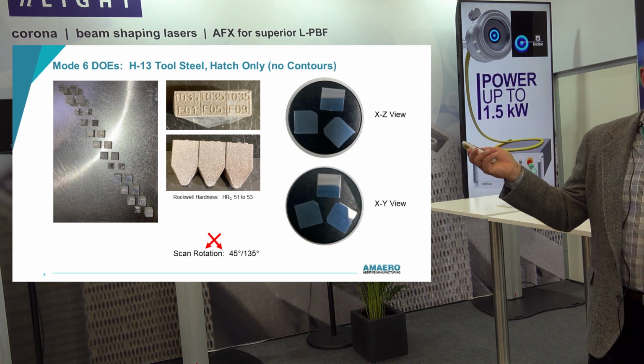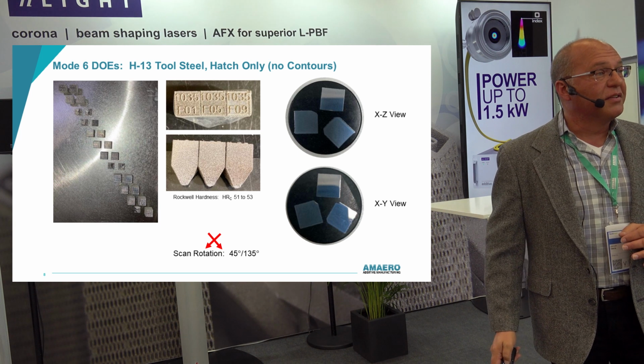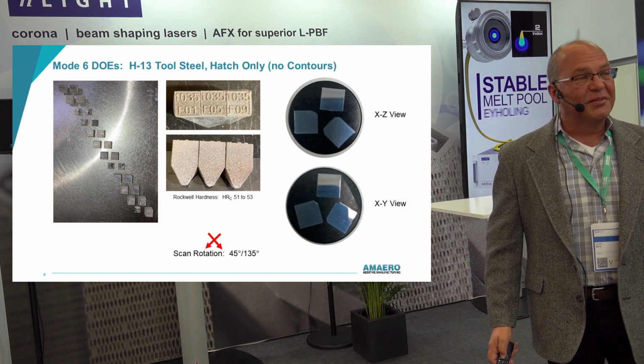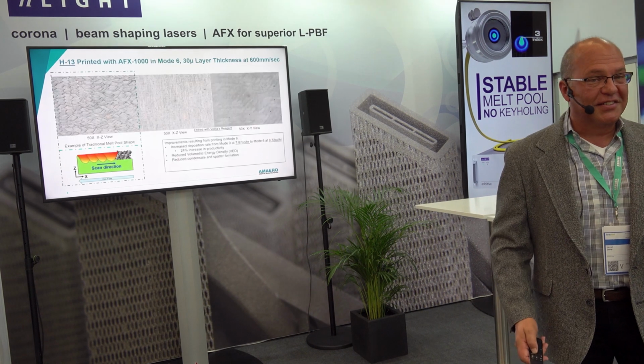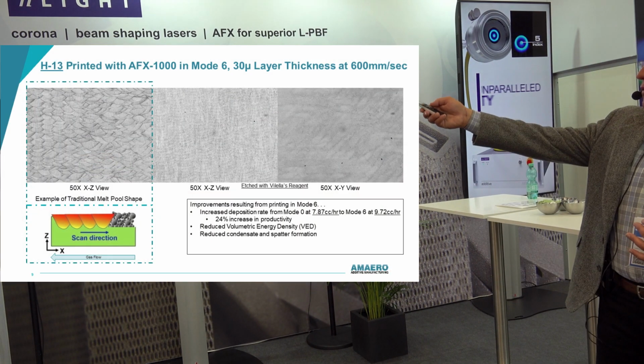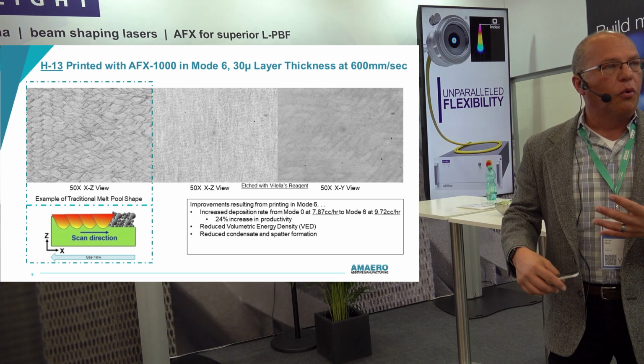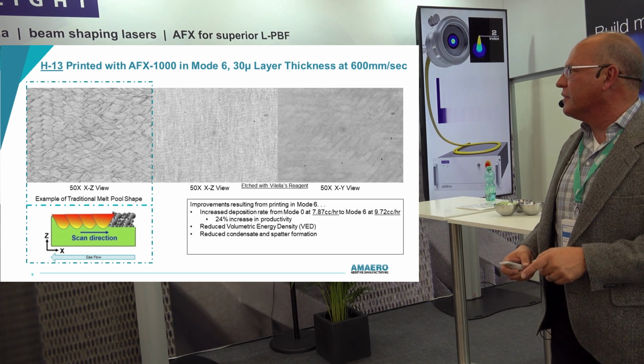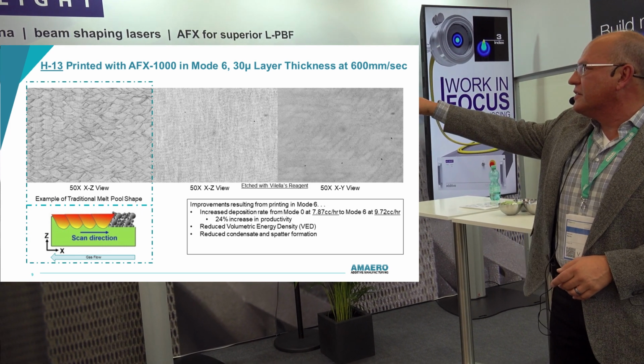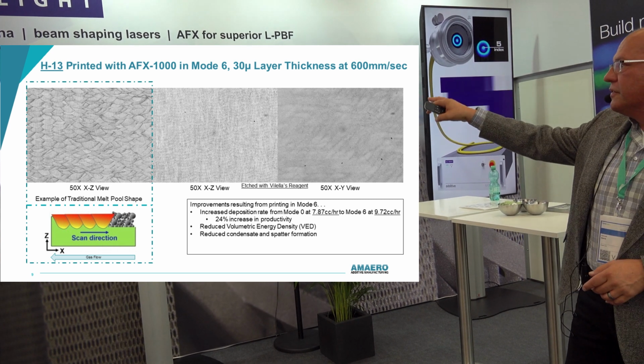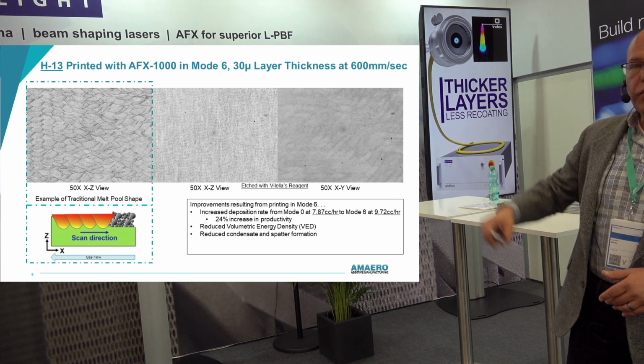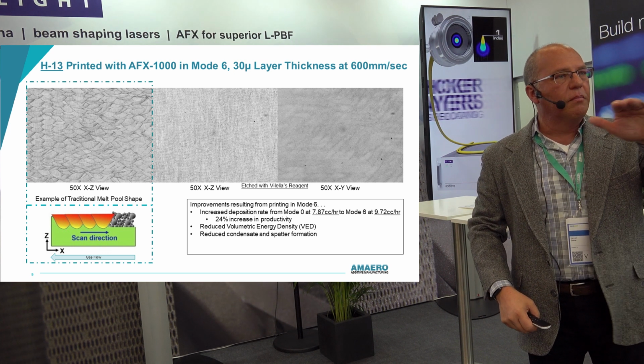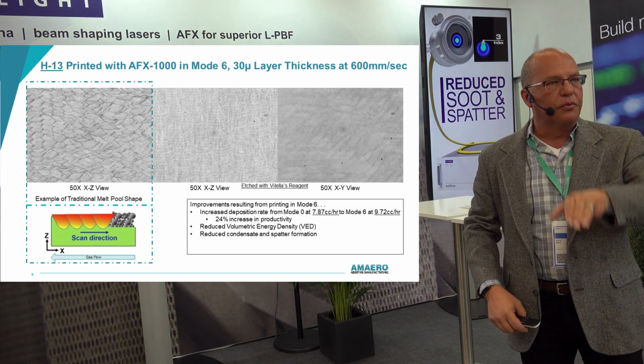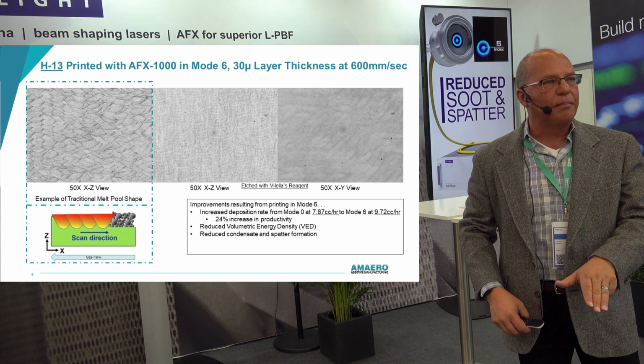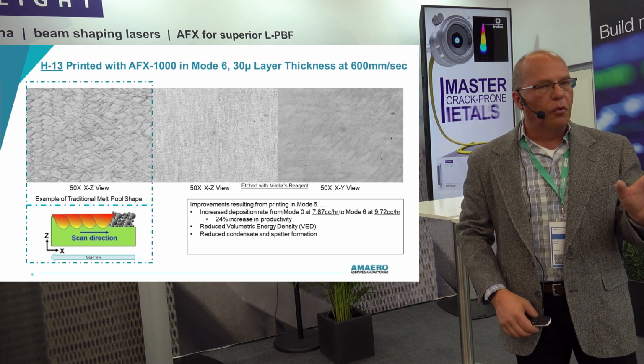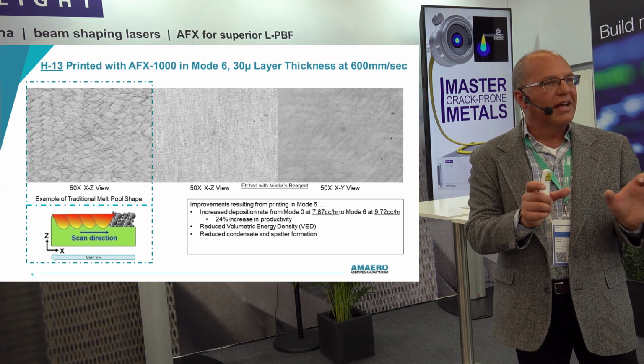And, oh, by the way, H-13 prints file hard. It's Rockwell C53. So all these DOEs, I have file hard steel that I have to section and do metallography on. So on the far left, that's the traditional melt pool that we're used to seeing, these very deep bells. And in the middle here, this is the H-13 in the XZ and the XY view. And what you see are these very, very shallow melt pools. They're not at all the deep pool that we're used to. There's no keyholing that's happening. And it's a nice wide, shallow pool, which means we can widen the hatch spacing.